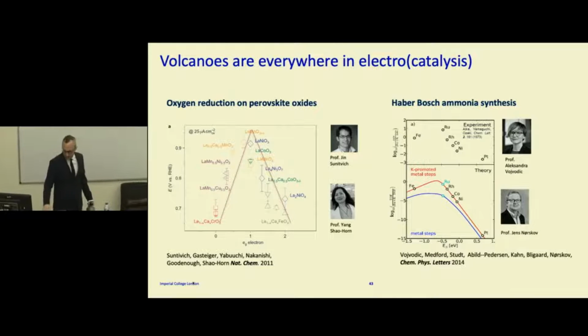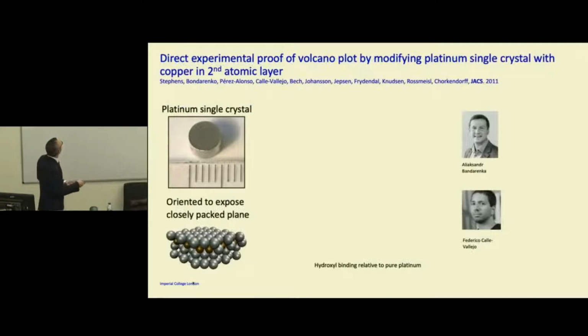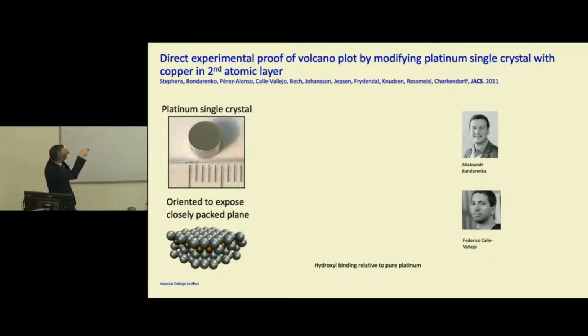One of the nice things we had at DTU was the ability to work with single crystals. Essentially, you can take a macroscopic crystal that has been oriented to expose almost entirely one crystal facet. So this is a closely packed plane of platinum. You can see all the balls closely packed together. And I was working with Alexander Bandarenko, a really good team in the lab, in our very rudimentary lab, actually.